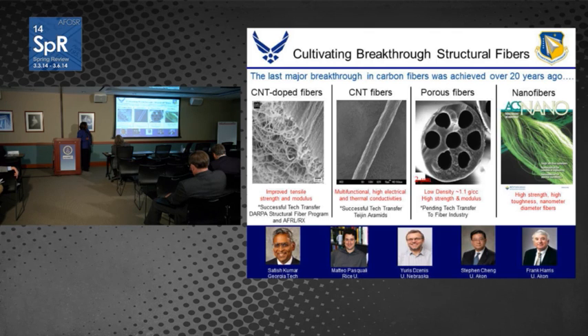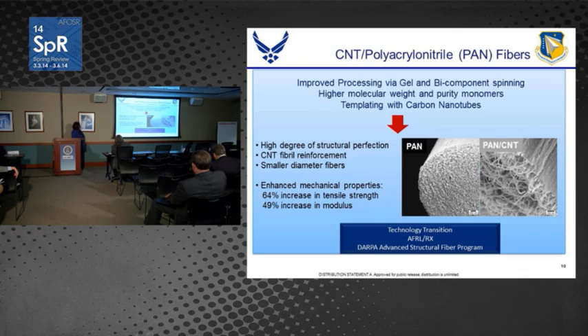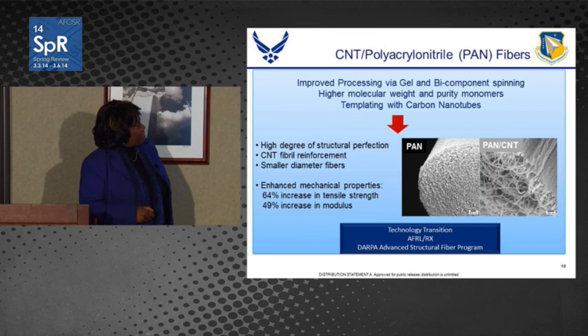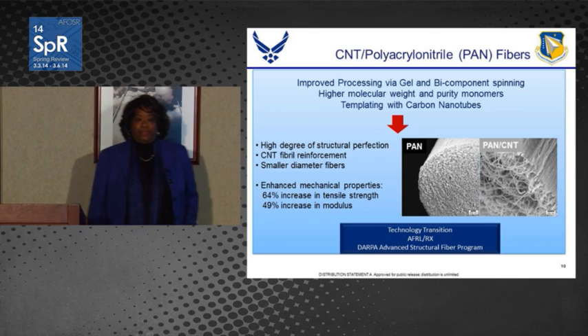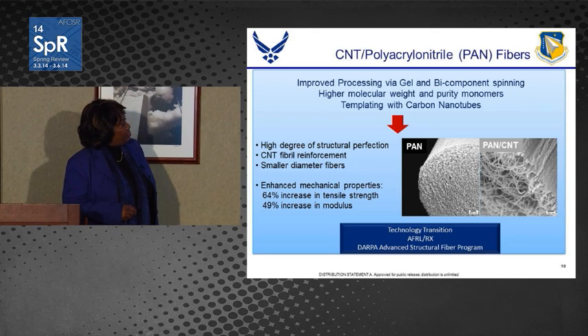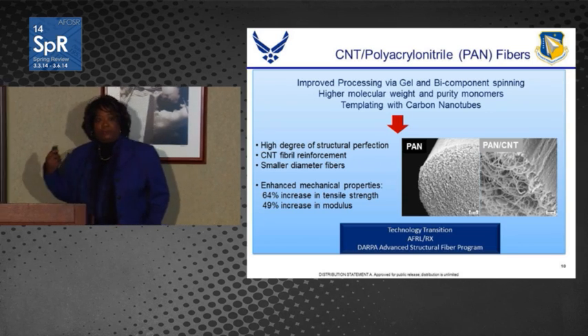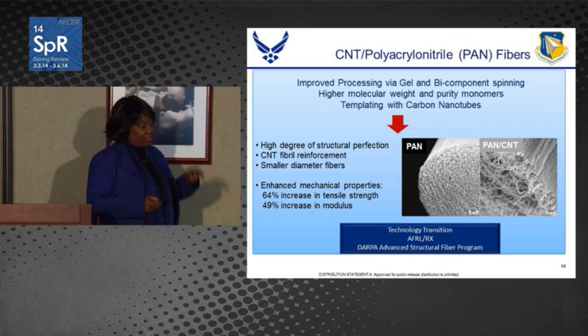But anyway, the first effort is the work of Dr. Satish Kumar at Georgia Tech, where he looked at doping polyacrylonitrile, PAN fibers. PAN is the high-performance polymer fiber precursor, and doping that with carbon nanotubes. And that templating with carbon nanotubes combined with other innovations like his bicomponent spinning process and increasing the purity and the molecular weight in these materials led to this templated, highly graphitic ordered morphology in a PAN carbon nanotube doped fiber, which led to real large enhancements in mechanical properties, approximately 50% enhancements in both the strength and the modulus in these materials. So this was a real significant advancement.